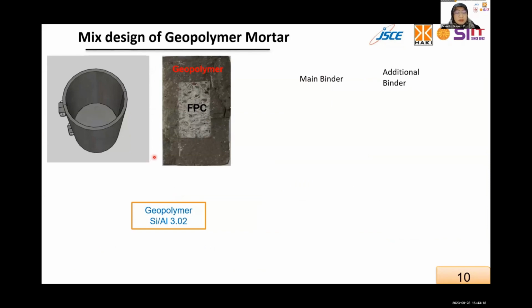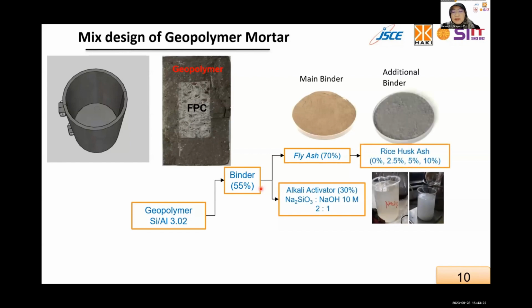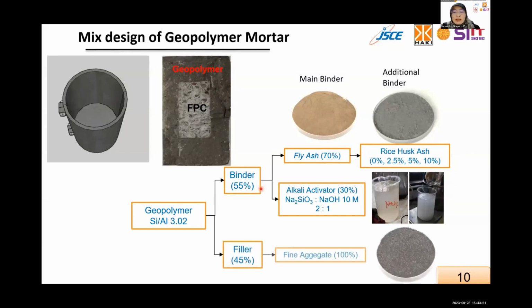And this is the conventional mixture of geopolymer mortar. We have binder. Binder mainly consists of the fly ash, and also we can put another cementitious material like rice husk ash, or we can also use GGBFS, blast furnace slag, and we can replace all the binder to replace the cement. And also we use alkali activator to replace the water. And as a filler, we can use fine aggregate or coarse aggregate, depending on our mix design. And this is the one that we made. The core is FPC, meaning Portland cement containing 20% of fly ash, and then surrounded by geopolymer mortars to cover it and to prevent it from the seawater.